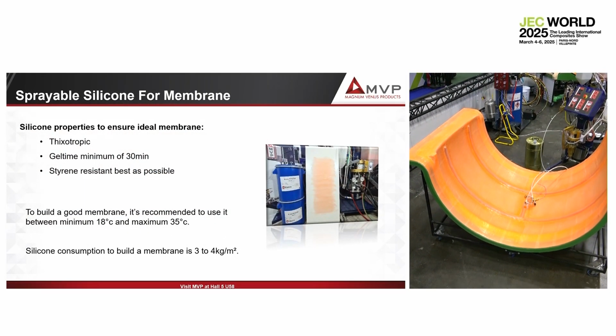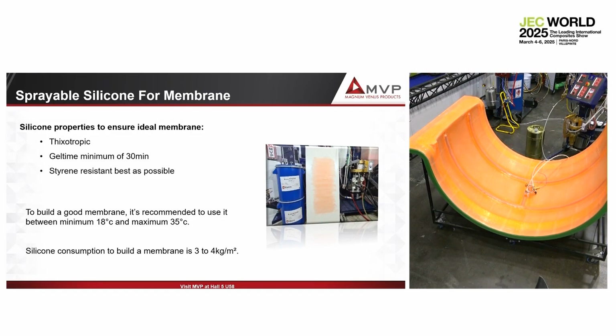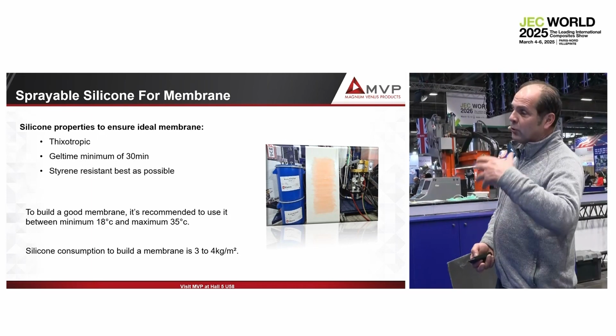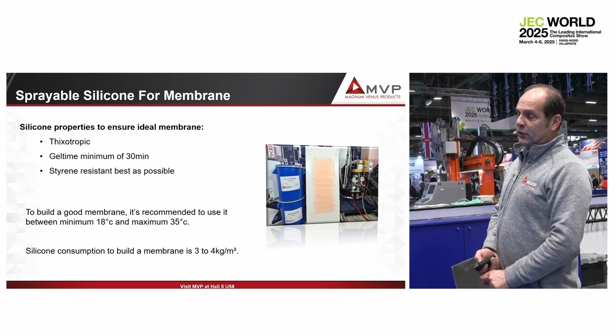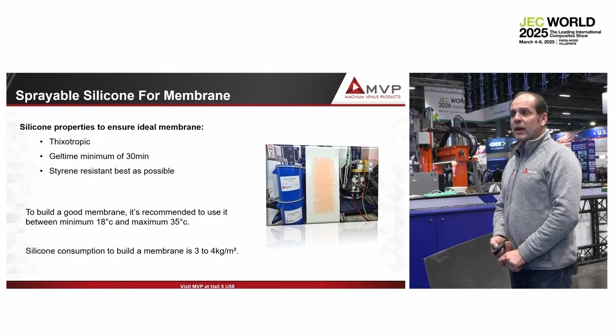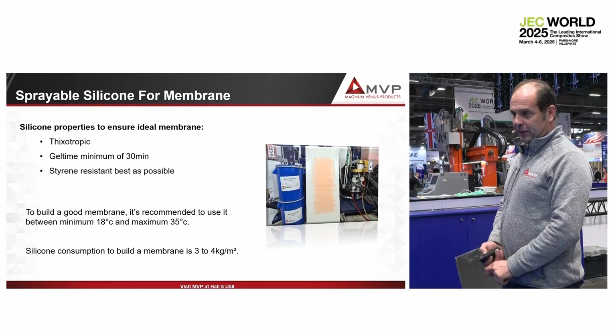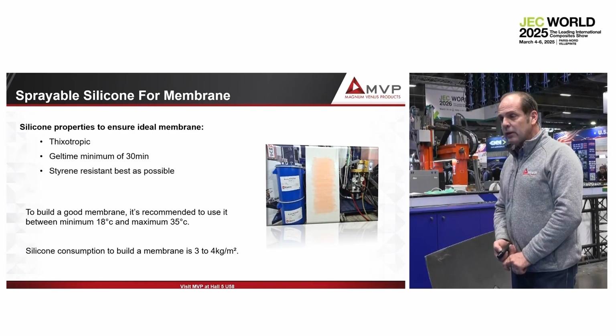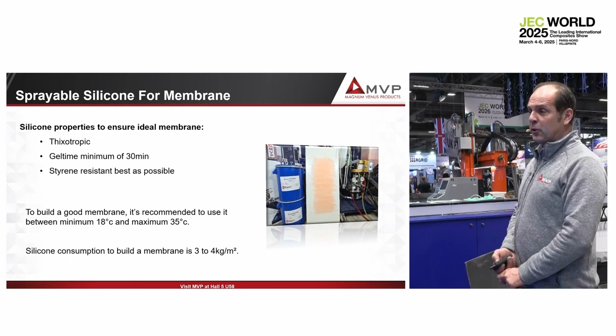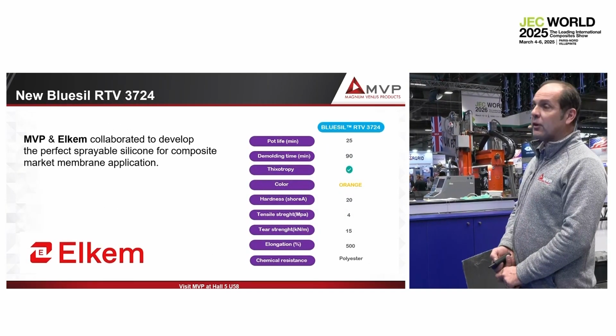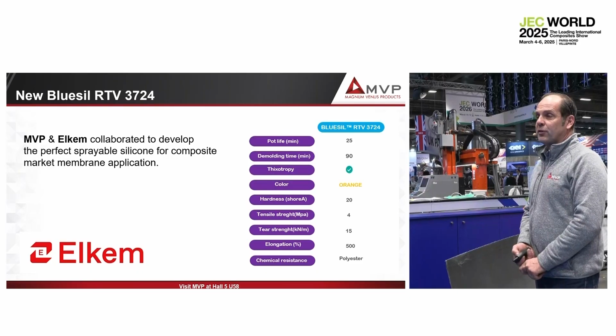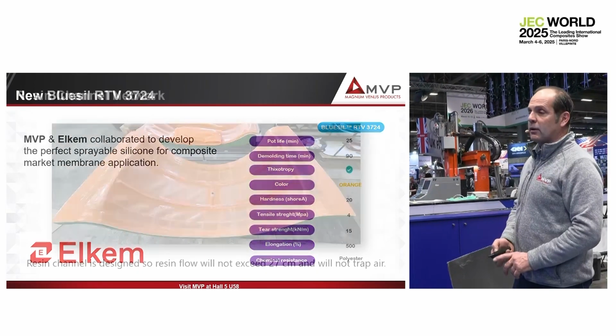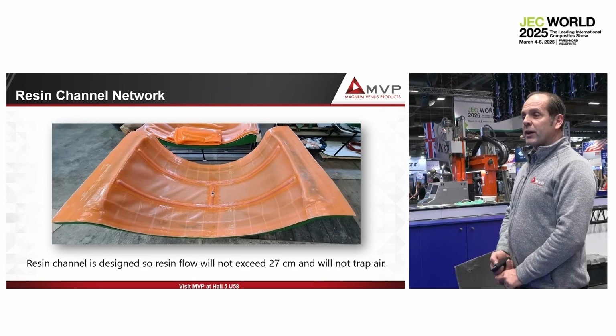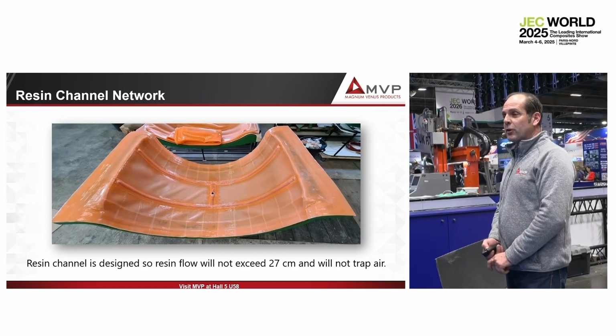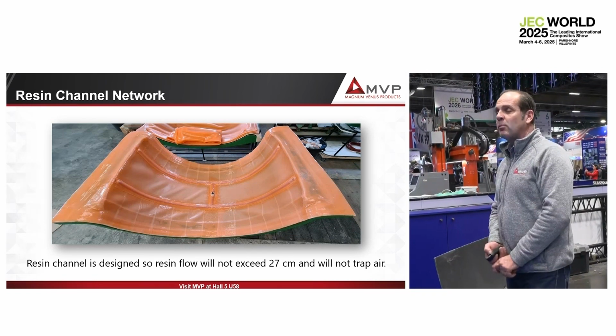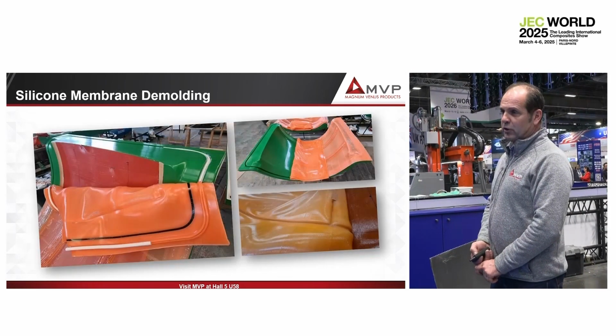So for that, we have used a sprayable silicone, which is the silicone from Elkem. We have worked with them to develop the right silicone, the right thixotropy, the right viscosity, the right gel time. And now we are developing with them a silicone that will be more epoxy resistant. The big problem with silicone is the amine that you have in the hardener of the epoxy. So we work on that, and that's the silicone Blue Sil RTV 3724 that we use today with normal polyester or vinyl ester resin. So then we have created the resin channel network to decrease the distance of the resin flow. The resin will flow for a maximum of 27 centimeters, which is okay.